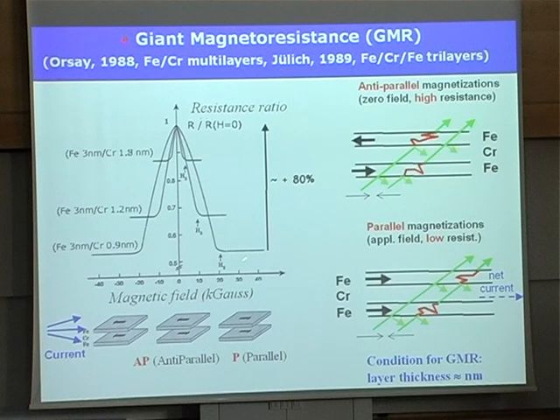The interpretation is what you can expect: when the magnetizations of all layers are parallel, for one of the spin directions the electron can go easily through all the magnetic layers and the resistance is low. This is a simplified description — you also have to take into account the reflection at the interface and the roughness of the interface — but more or less the concept is very simple.